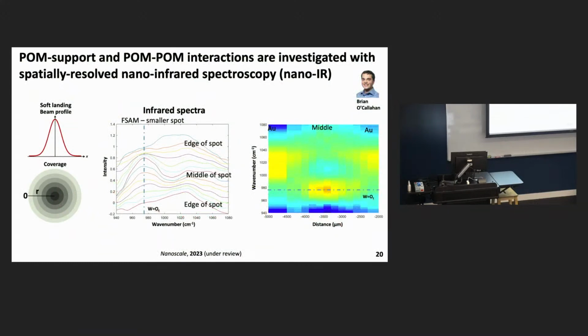One thing that's also nice about this soft landing technique is it allows you to prepare a surface with varying coverage. And this is because your beam has a Gaussian intensity profile. So the center of the beam is most intense, and it falls off in a bell-shaped curve toward the edges. So when you integrate that over a deposited spot, you end up with something that has high coverage at the center and lowest coverage towards the outside.